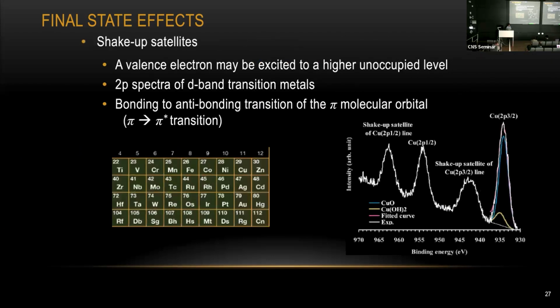And the next final state effect is called a shake-up satellite. Sometimes you might see some additional signal in your spectrum, which doesn't give you any information. It's simply some satellite peak. You are going to see those satellite peaks very often if you're working on transition metals. If you're doing a measurement on this kind of material, sometimes you might see some additional satellite peak.